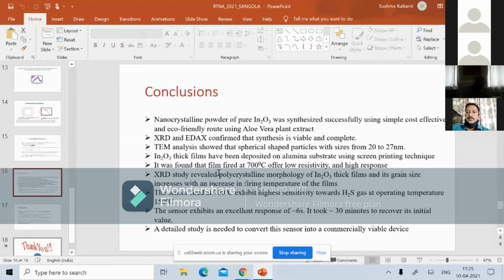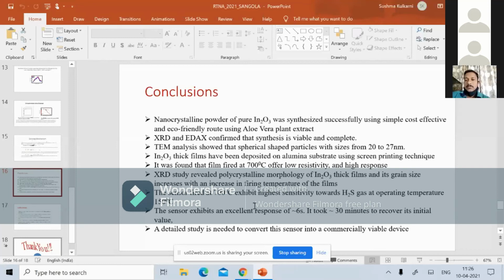It was found that the film fired at 700 degrees Celsius offered low resistivity and high response. The XRD study revealed the polycrystalline morphology of the In2O3 thick film, and its grain size increases with an increase in the firing temperature of the film. The sensor fired at 700 degrees Celsius exhibits the highest sensitivity toward H2S gas at an operating temperature of 150 degrees Celsius.